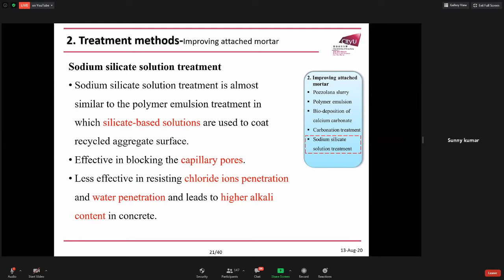The last treatment method for improving attached mortar is sodium silicate solution treatment. This treatment is almost similar to the polymer emulsion treatment, in which silicate-based solutions are used to coat the recycled aggregate surface. It is effective in blocking the capillary pores, but it is less effective in resisting chloride ion penetration and water penetration, and it leads to higher alkali content in concrete.